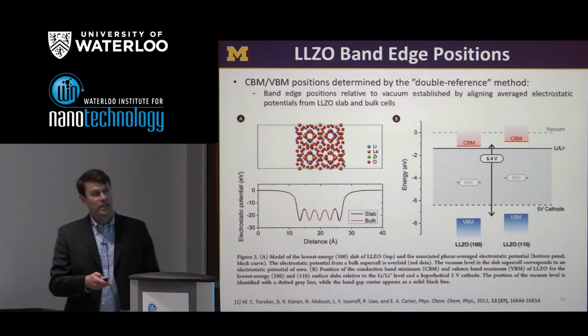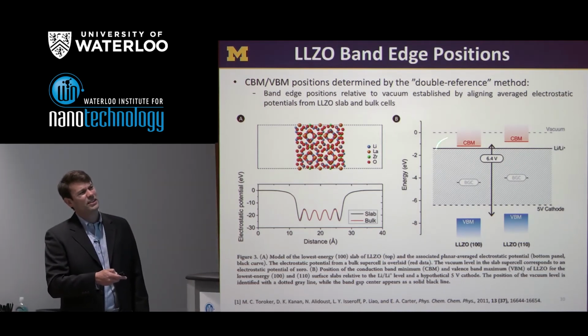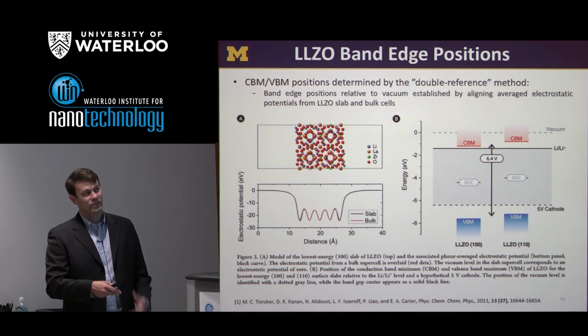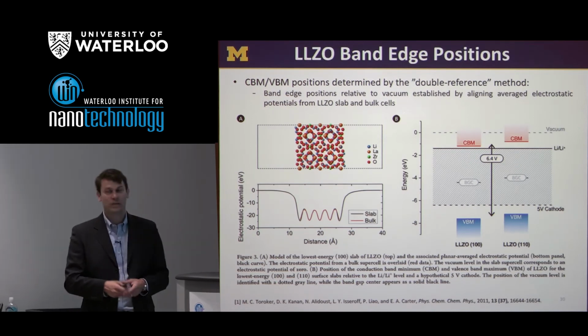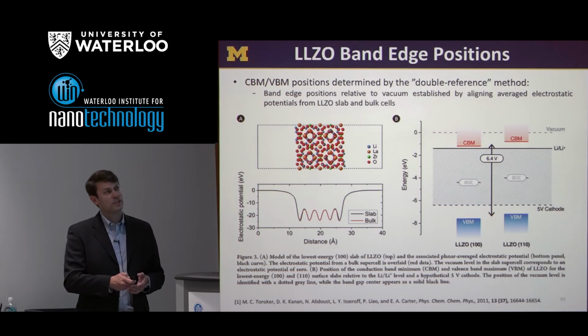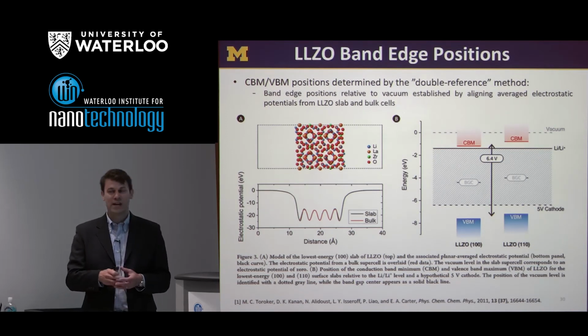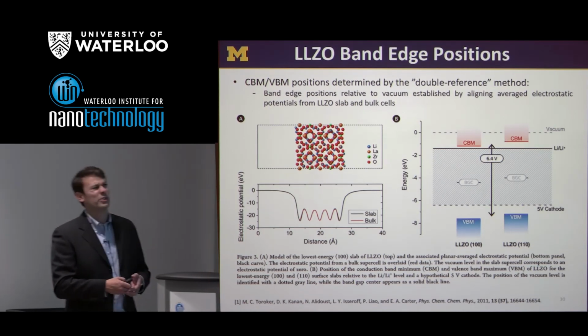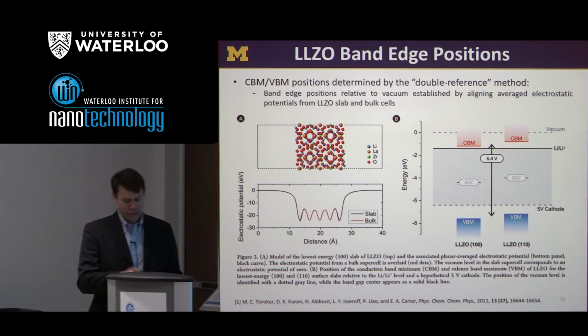And I can tell you more later if you like, but basically the upshot is that in particular we should focus on what's happening up here with respect to the conduction band minimum, because these calculations are focused on equilibrium with lithium, so equilibrium with the negative electrode. What we find is that for LLZO, it looks like the conduction band minimum is actually slightly above the lithium/lithium plus level. So that's really good news.